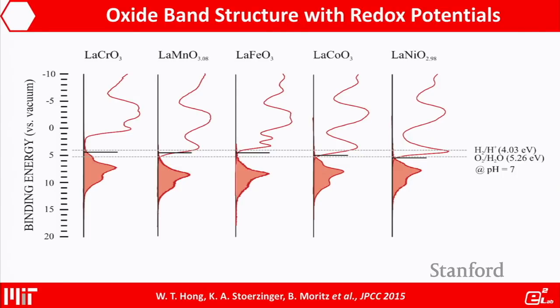On the bottom, the shaded area is the occupied density of states measured by emission, and the unfilled part is the unoccupied states measured through X-ray absorption spectroscopy. We can line up the density of states onto the same energy level and align them onto the absolute energy scale. Once you align them on the absolute energy scale, you can align the redox potentials of the solution species onto the same common energy scale, the dashed lines being the hydrogen redox and oxygen redox. So from this picture, you can begin to develop energetic arguments. What is the barrier for my electron transfer? What is the energetics for hydroxylation of my surface?